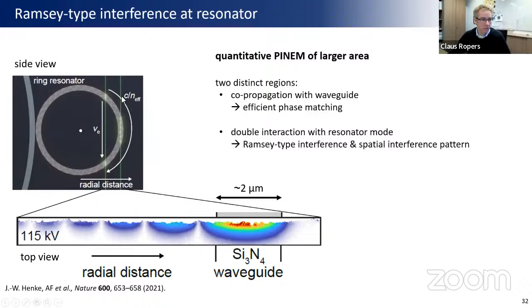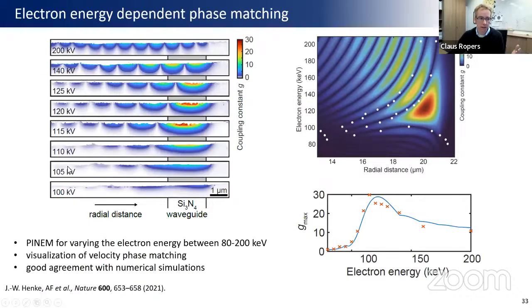You see, as you scan the electron beam across the circumference of these structures, you actually see an oscillatory pattern, which is just a phase mismatch by interacting with two different locations of the structure. You can do this as a function of energy and then fully characterize this optical field. And again, this is an intracavity optical field exclusively probed with an electron beam at very high spatial resolution.